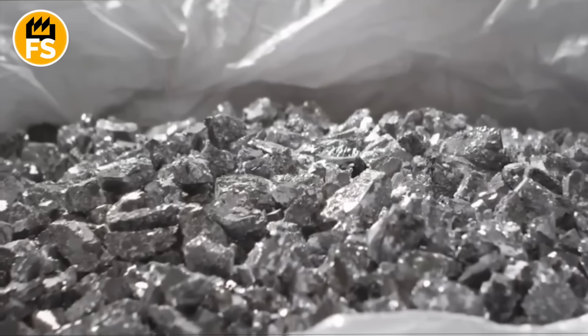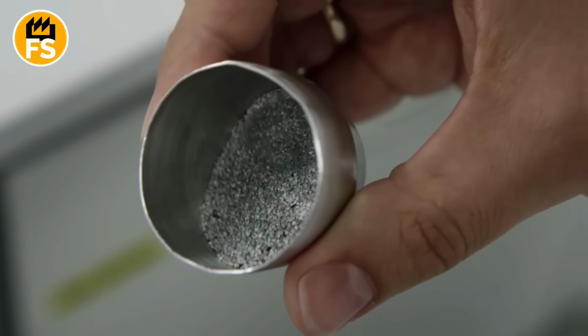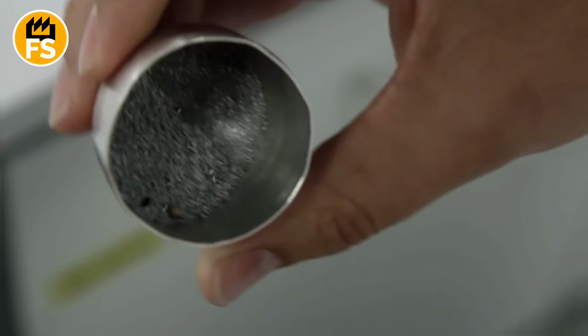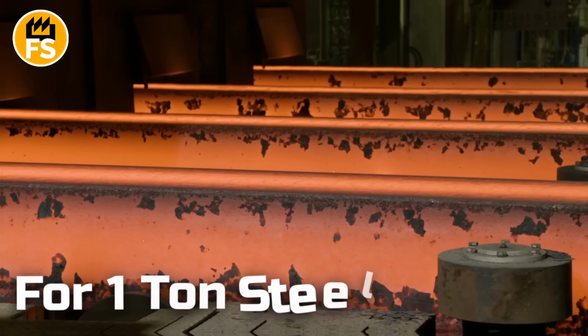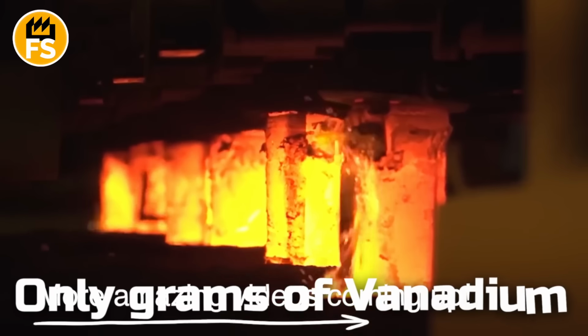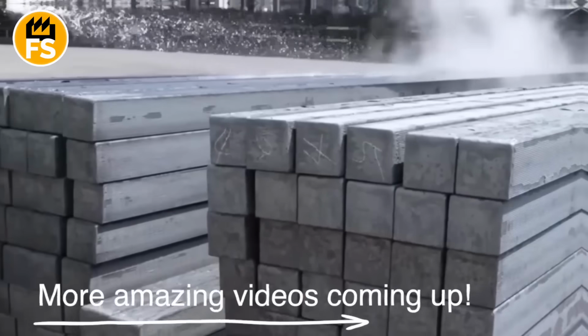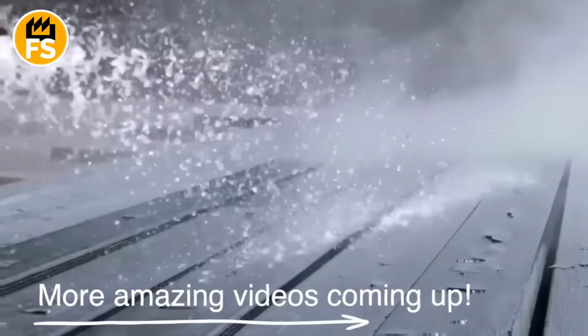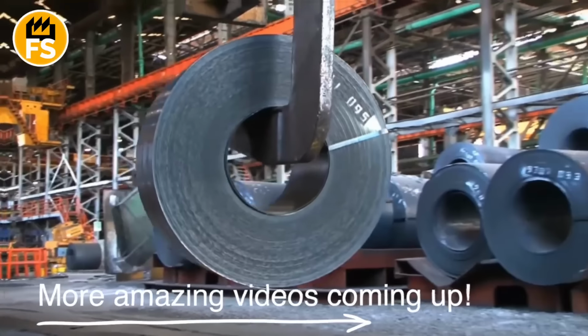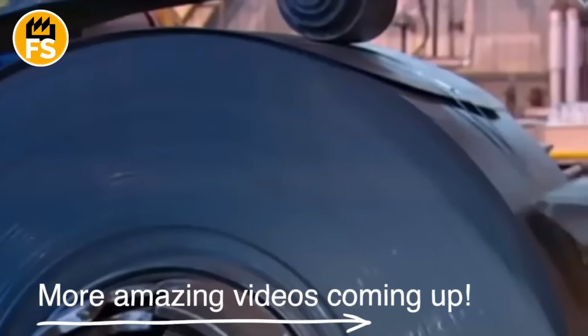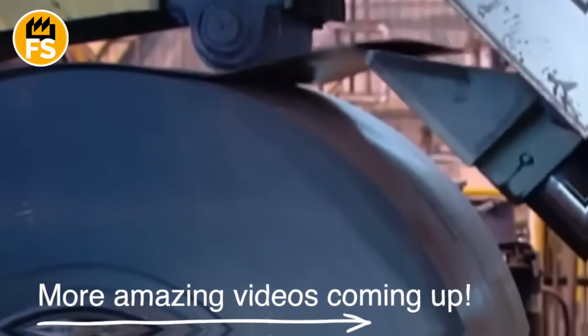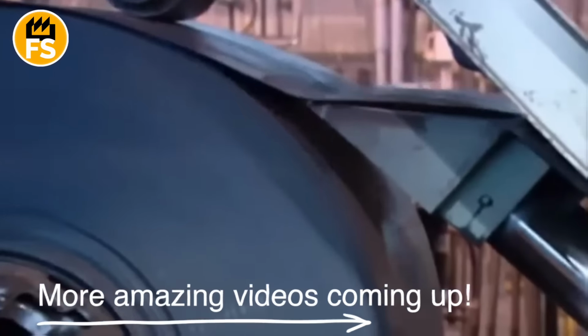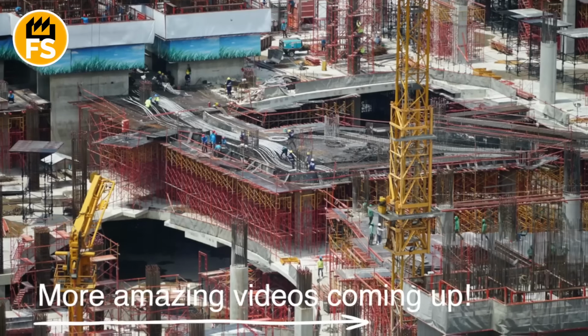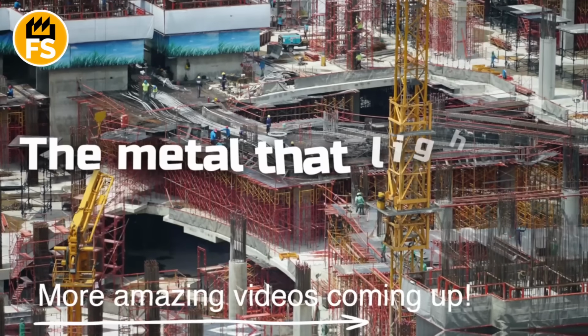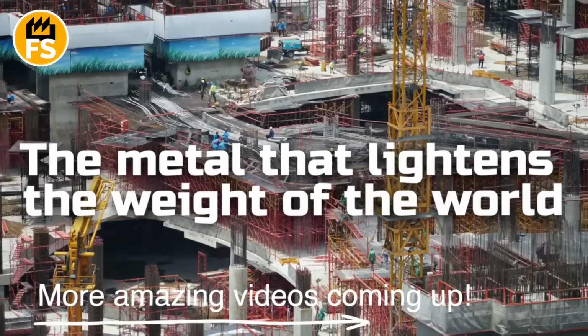To get a noticeable effect, just tenths or even hundredths of a percent are enough. This means that for 1 ton of steel, only grams of vanadium are used, but those grams can boost yield strength, toughness, and durability by tens of percent. At the scale of millions of tons of steel, this delivers massive savings in metal, energy, and transportation costs. That's exactly why vanadium is often called the metal that lightens the weight of the world.